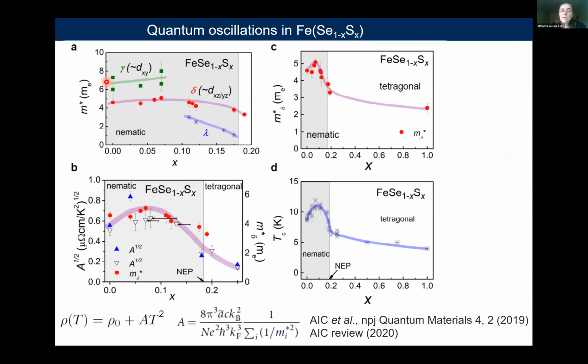So we have a mass of about 5, which slightly increases, but we can follow the delta band all the way. We can't say too much about what happens to the dxy band, but in quantum oscillation, if something is heavier, it's harder to observe. We also think at some point these orbits become quite similar, so it's very hard to reveal the behavior of the dxy band from quantum oscillations because of its heavier mass and its close proximity to the delta band.